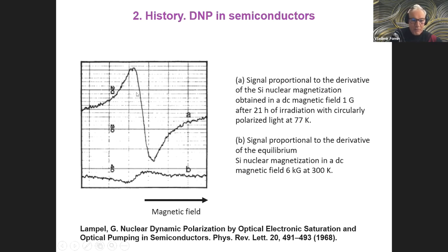This is the upper curve. It's the derivative of the EPR response or NMR response. The lower line is a signal proportional to the derivative of the equilibrium silicon nuclear magnetization in a magnetic field of 6 kilogauss. Please compare these two numbers. This is 1 Gauss and these are 6,000 Gauss. And in the first case, due to this dynamical nuclear polarization, the signal is enhanced by more than